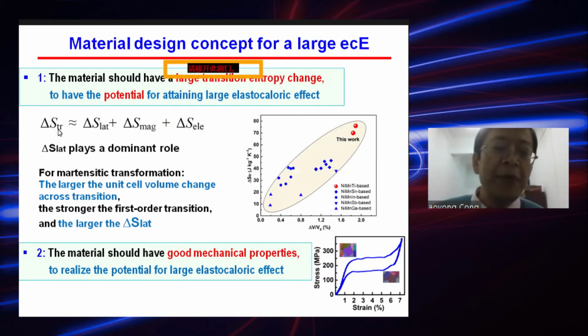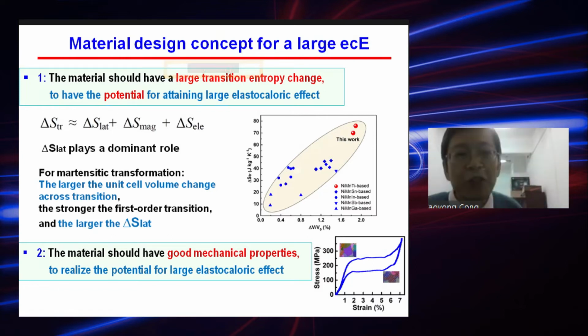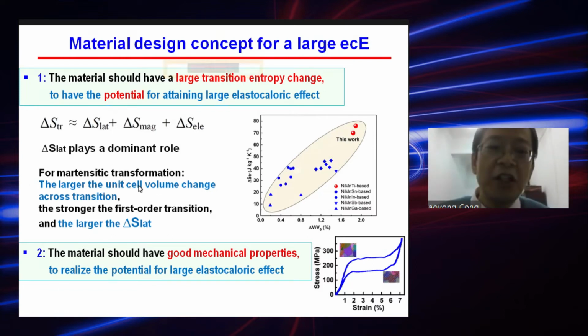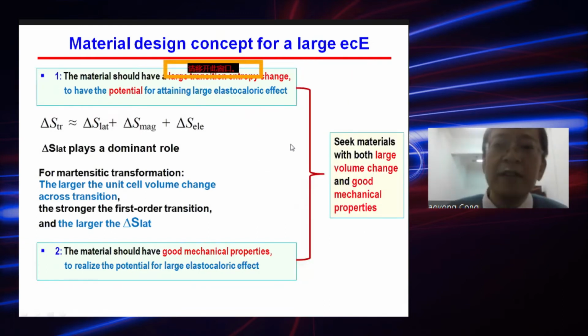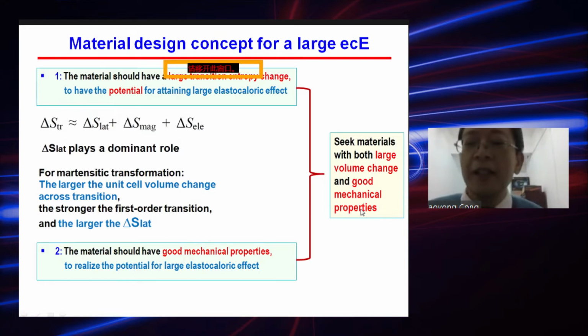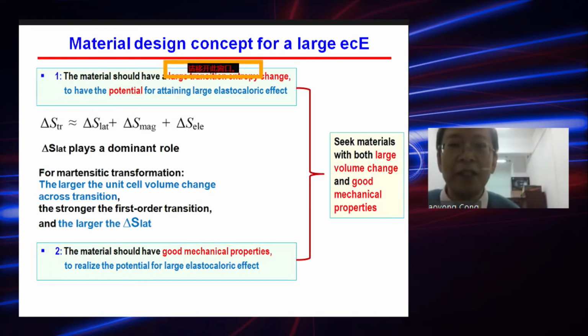As we know, for shape memory alloys, the transformation entropy change consists of 3 parts: lattice entropy change, magnetic entropy change, and electronic entropy change, among which the lattice entropy change plays a dominant role. Especially for martensitic transformation, the larger the unit cell volume change across transition, the stronger the first-order transition, and the larger the lattice entropy change. Therefore, the problem becomes that we seek materials with both large volume change and good mechanical properties in order to get a large elastocaloric effect.